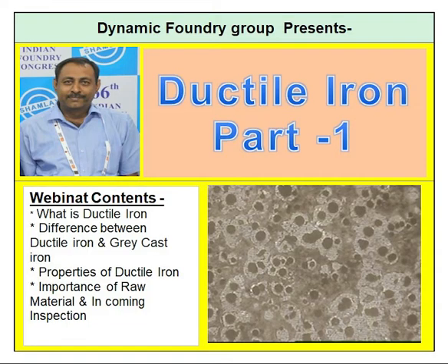I am not going into detail of that control because we are not talking about raw material inspection here, but just to conclude, I will say in CRC you have to control the manganese, you have to control the bundle size, you have to control inside bundle material, like if MS is there or some other plating is there. You have to control those things to a high degree, because if something goes in from the bundles, it is very difficult to control the whole melt composition at the end of the bath, because you cannot dilute those kinds of things. So control on CRC is very important, particularly manganese, chromium, and some of the trace elements which are present in the various scrap material. So you have to control CRC for that. Your raw material inspection method should be good, and most importantly, you should continue with a reliable source of supplier.